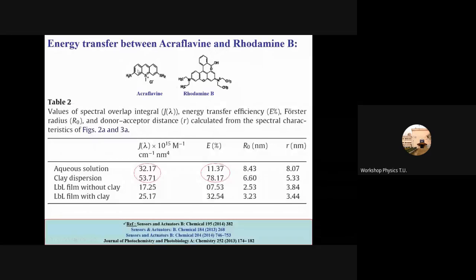Again, here is another example with acriflavine molecule and then rhodamine molecule. This is the donor, this is the acceptor. Here, in aqueous solution, we have seen that energy transfer efficiency was 11.37%, but when we put clay, in clay dispersion, efficiency becomes 78%, almost 7 times. And this is again because the distance is lower, from 8 to 5.33 nanometer.